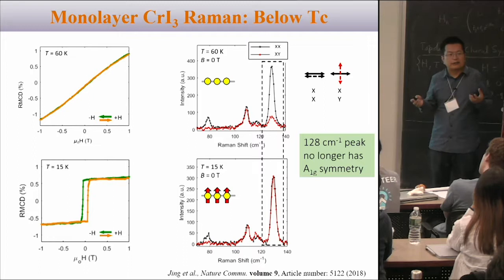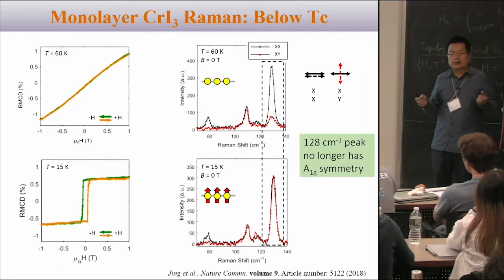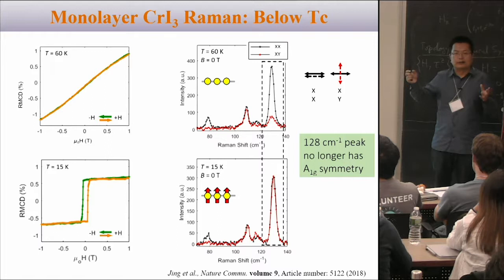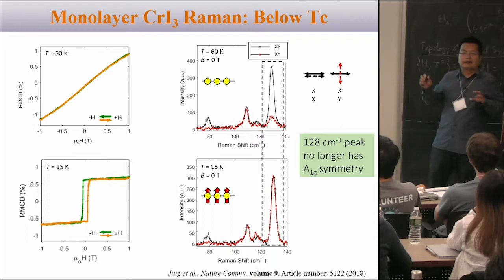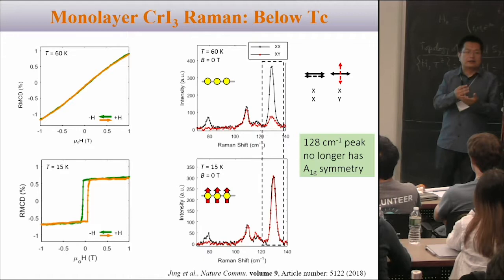This is not too difficult to understand. When you have magnetic order, if you think about conductivity measurements — if you have magnetism or time reversal symmetry breaking, you should have an off-diagonal term. You can see the Hall conductivity, the Hall component, in a transport measurement. This is a similar concept in the Raman tensor: when magnetic order comes into play, you introduce a Hall-type component in the off-diagonal terms. That's why you see this off-diagonal contribution in the XY channel in the Raman scattering.